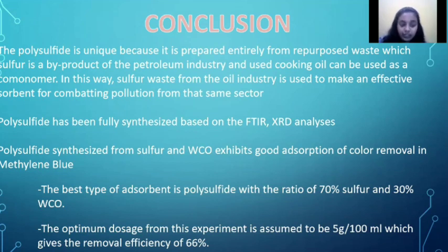And polysulfide, which has been synthesized from sulfur and waste cooking oil, exhibits good adsorption for color removal of methylene blue. The best type of polysulfide that we obtained from this project is 70% sulfur and 30% waste cooking oil. And the optimum dosage was found to be 5 gram in 100 ml of methylene blue solution.